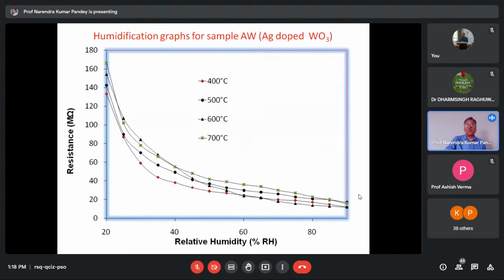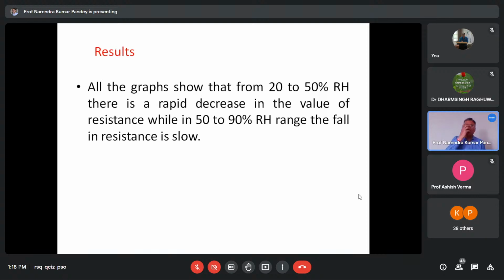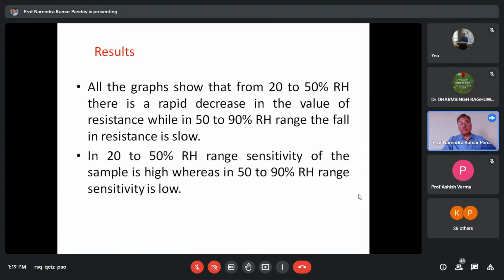And if you see the same one, what do you see? All the graphs show that from 20 to 50% RH there is a rapid decrease in the value of resistance, while in the 50 to 90% range, the fall of the resistance is low. In the 20 to 50% range, the sensitivity of the sample is very high.